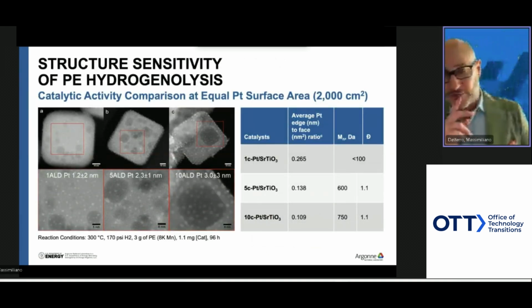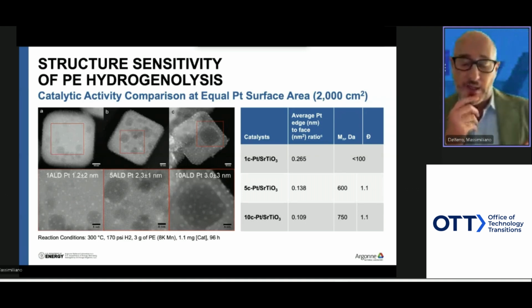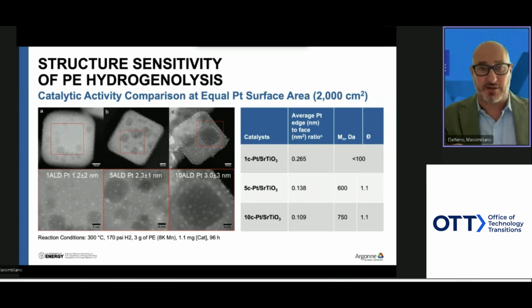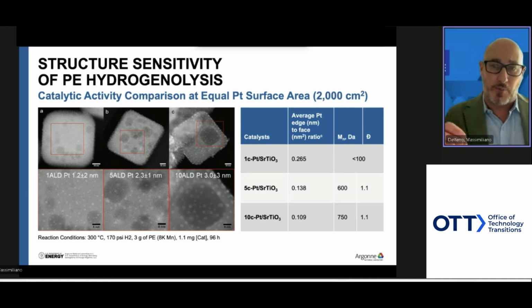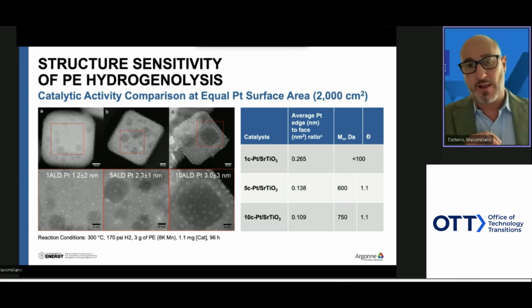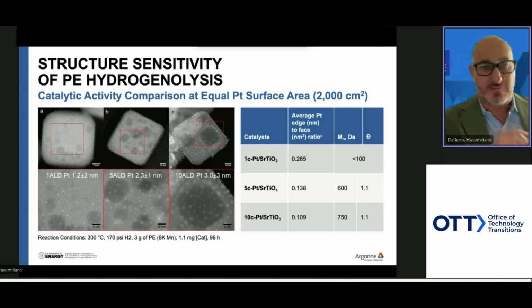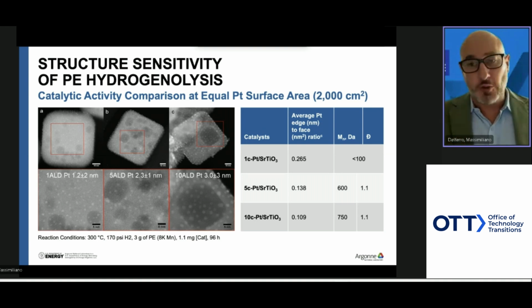The reaction, as I mentioned before, is called hydrogenolysis. It is a structure-sensitive reaction. That means that by controlling the particle size, in this case of platinum, we can control the dimension of the nanoparticles, and the dimension of the nanoparticle provides a different product. For example, we can go from gases for very small nanoparticles to, for large nanoparticles, waxes or white oils. And this gives us really a fine tuning of the product that we want to make based on the catalyst design.